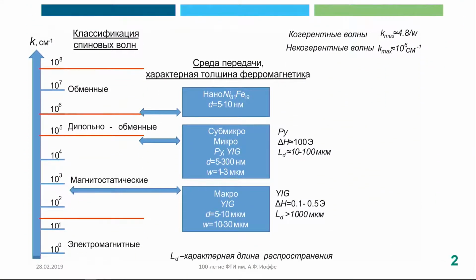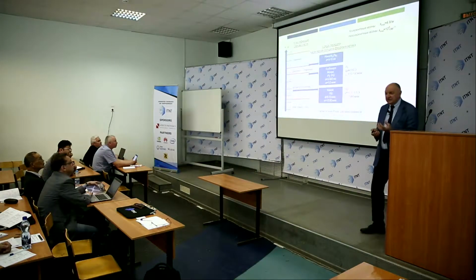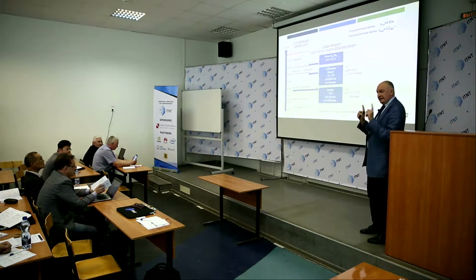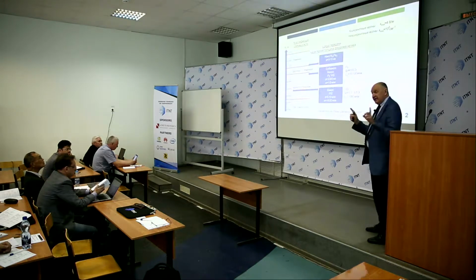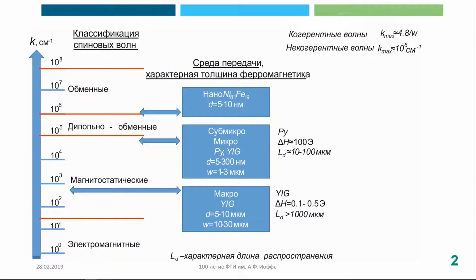So spin waves or magnons, this is the classification of spin waves. Starting from electromagnetic waves, you go to so-called magnetostatic waves, when you use for description of spin waves the Maxwell equations in the so-called magnetostatic approximation. So these are wavelengths smaller than electromagnetic waves. However, they are still not related explicitly to the magnetic structure of the material. But if you consider so-called dipole exchange waves, when you consider already interaction between two related atoms with magnetic moments, so they operate with exchange interaction between them, and the wave numbers can be 10 to the 5, 10 to the 6, therefore wavelength goes down to 1 micron or even less than 1 micron. And pure exchange waves operate with these wave numbers, therefore this is submicron or even nanometer scale of wavelengths.